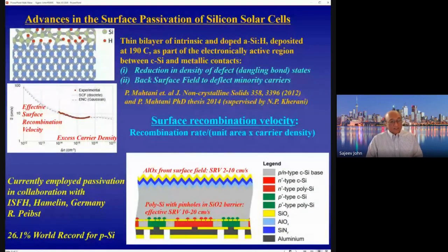And for recombination to take place, both carriers would have to be present. And with this surface passivation technique, they have shown that the recombination can be reduced quite a bit. That is measured by something called the surface recombination velocity. The meaning of surface recombination velocity is the recombination rate per unit area per unit carrier density. That actually has the units of velocity.